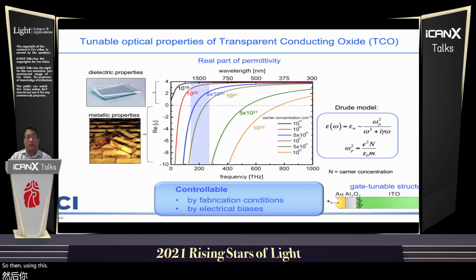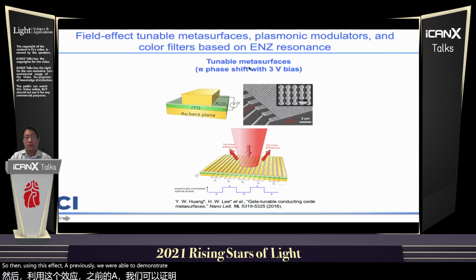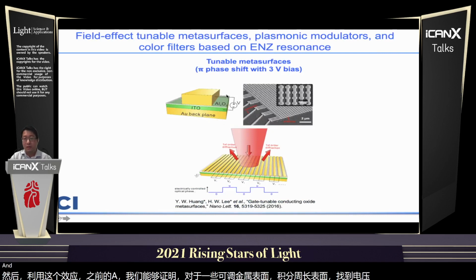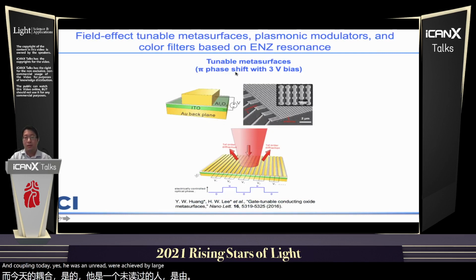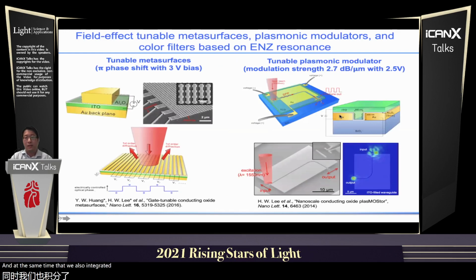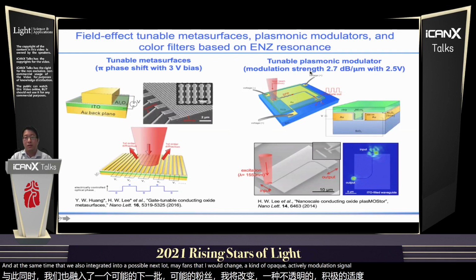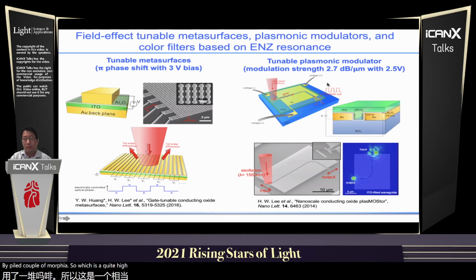Using this effect, previously we were able to demonstrate, for example, making a tunable metasurface, integrating to a metal surface, applying the voltage, and coupling to the ENZ resonance, we were able to achieve quite large pi phase shift modulation, applying a couple of volts here. And you can use this tunable metasurface to beam steer the light actively as well. At the same time, we also integrated that into a plasmonic slot waveguide so that we can apply the voltage, actively modulating the signal. And we got a modulation strength of about 2.7 dB per micron by applying a couple of volts here, which was quite a high modulation strength at that time, one of the highest you can find in a plasmonic modulator.